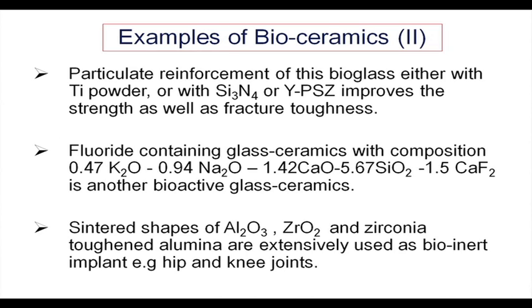Now, sintered shapes of Al2O3 and ZrO2 and zirconia toughened alumina. These are pure alumina, this is pure zirconia, but a combination of that is also used as a composite material, where zirconia is used as a toughening phase in alumina, and is extensively used as bio-inert implants, for example hip and knee joints. So, primarily for joints which need some friction and a lot of movement, this kind of relatively high strength ceramics, but inert materials, are more useful.